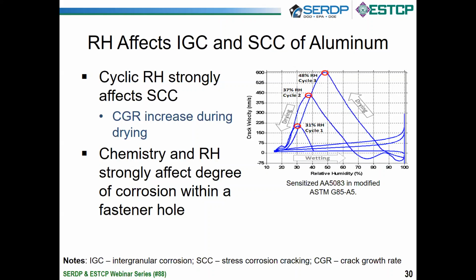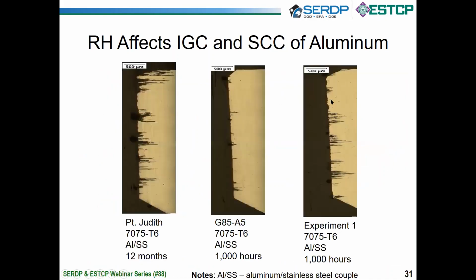Let me note that this is data from the G85A5, so the dilute chloride and pH of about 5. And you might say, oh, well, this is a sensitized, and this is a pretty highly sensitized 5000 series alloy. But Luna has done work on 7000 series alloys, and you still see the same kind of effect. In fact, up to a factor of 10 if you're looking at some of the fatigue data that's not shown in here from other work that we know. So both the chemistry and cycling the RH strongly affect what's going on at cracking as you dry.